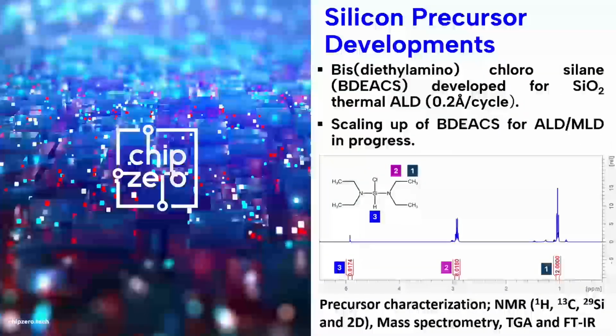And the second precursor we were working on is BDEACS. So we were able to develop these precursors in a small quantity, but now we are focusing on the scale up of these precursors. Also, we were able to show that we could utilize these precursors for thermal ALD of silicon dioxide.